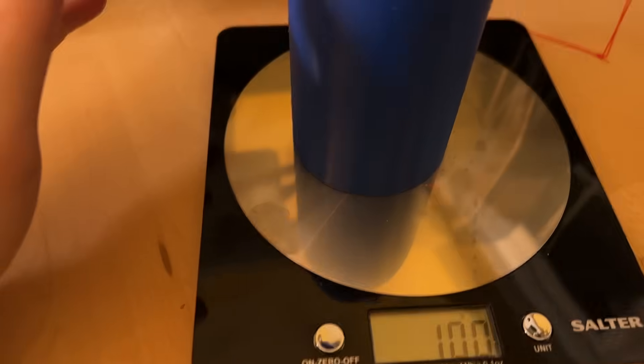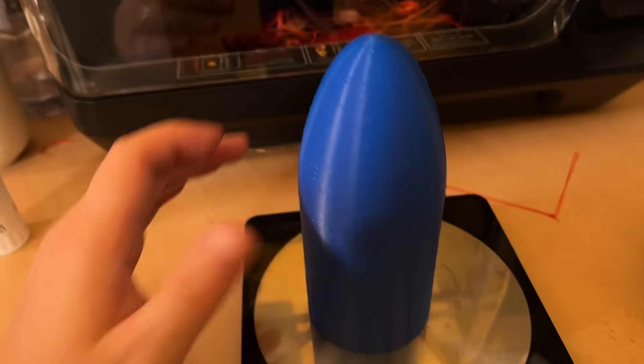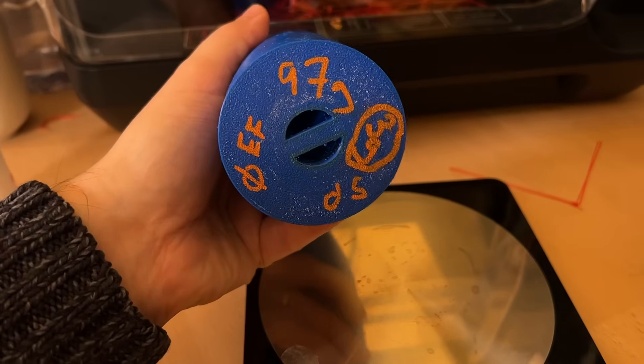Okay, it looks like it's taken on only 3 grams of water, which is about 10% as much as the best uncoated sample I tested last time. How exciting is that?